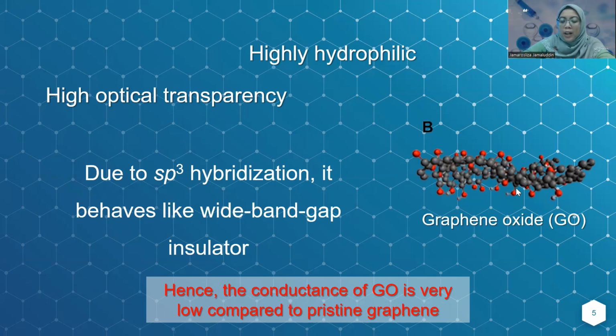The sp2 hybridization of pristine graphene is partially converted to sp3 hybridization in graphene oxide. This results in the material behaving more like a wide band gap insulator than a conductor, with low electrical conductance compared to pristine graphene.